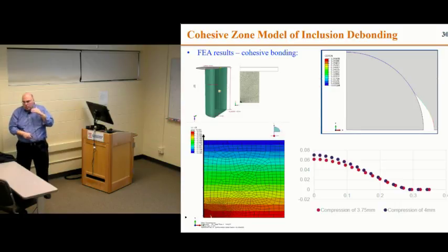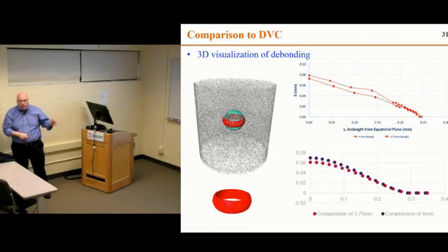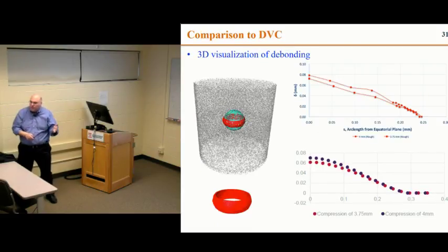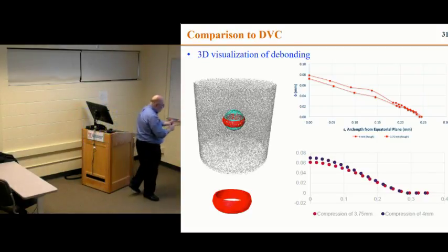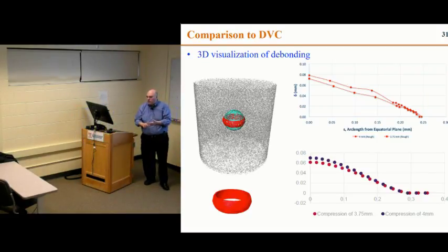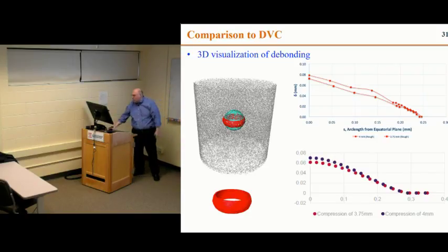So what we would like to do is compare this measurement with what we get in the experiments. And that is something that we can actually obtain and measure in addition to displacement fields. So load displacement would have to match, displacement fields would have to match, and also things like the failure profile would have to match. This is the same thing I had from the slide before.